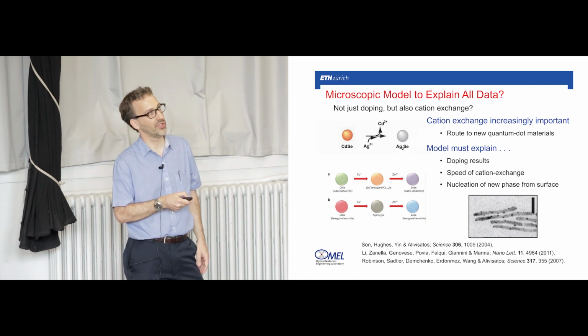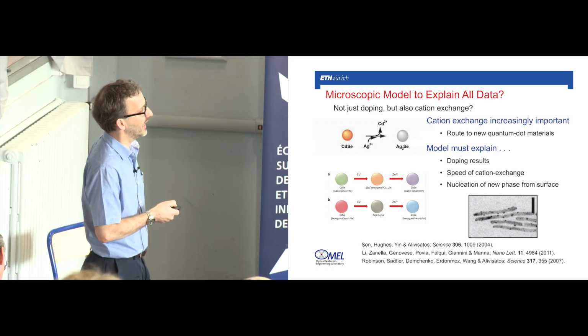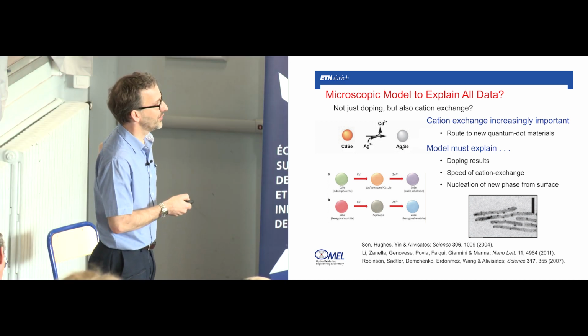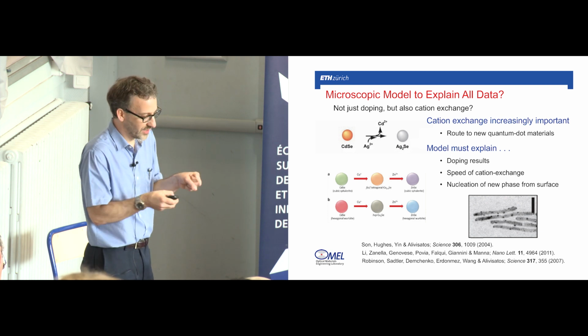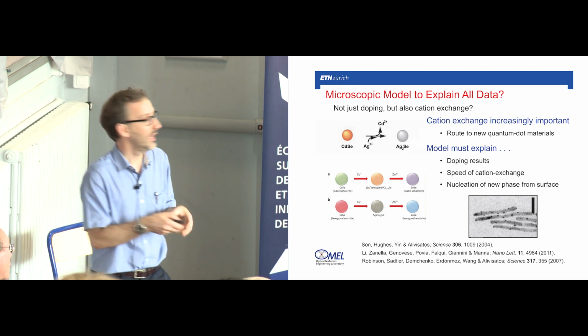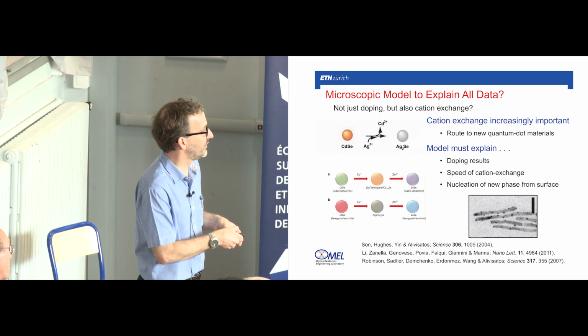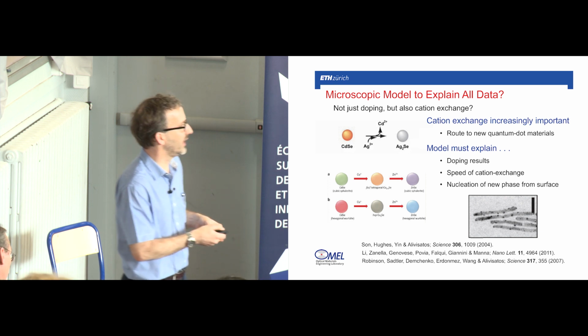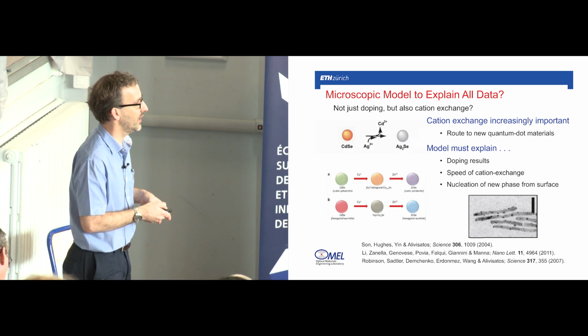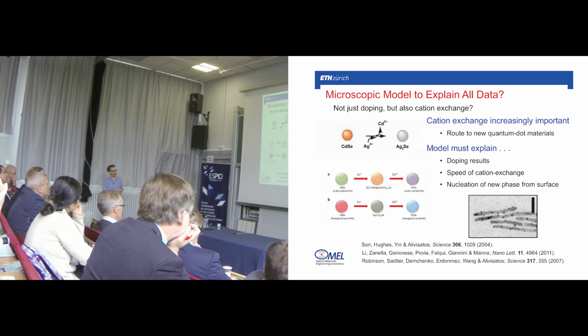And so our model should explain the doping results, the speed of the cation exchange reaction, and also this data from the Alivisatos group where they tried to freeze the cation exchange early on, and they saw these little seeds of silver sulfide that were nucleating on the surface of these nanorods. And so our model has to try to explain all of these different results.